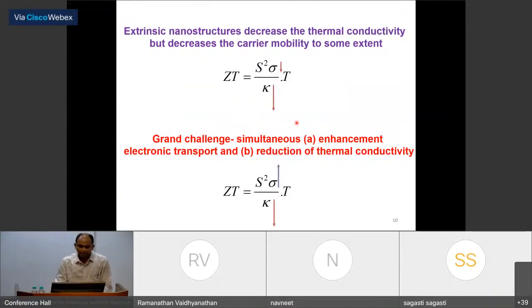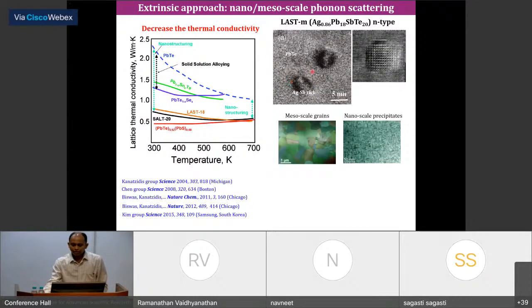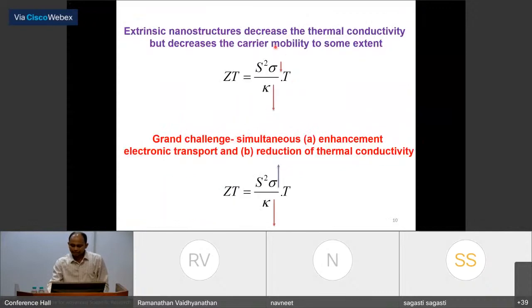But the challenge remains with this extrinsic nanostructuring, that the thermal conductivity decreases heavily, but we see a decrease in the electrical conductivity because there is a mismatch between lattice strains and lattice parameters, which scatters the electron or hole and decreases the electrical conductivity. So this is the grand challenge of the field that has remained for the last 10 years, a decade-long challenge, because we always have a decrease in thermal conductivity, but we compromise with the electrical transport, the electrical mobility and the electrical conductivity. Now, we want to have simultaneous enhancement of the electronic transport and reduction of thermal conductivity.